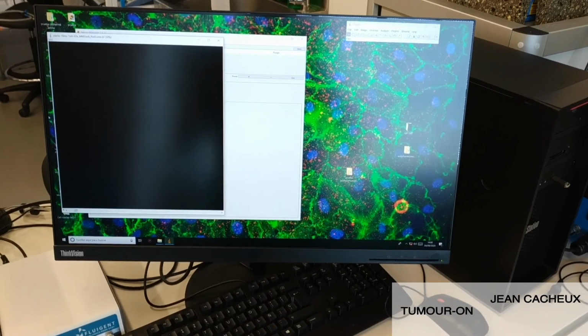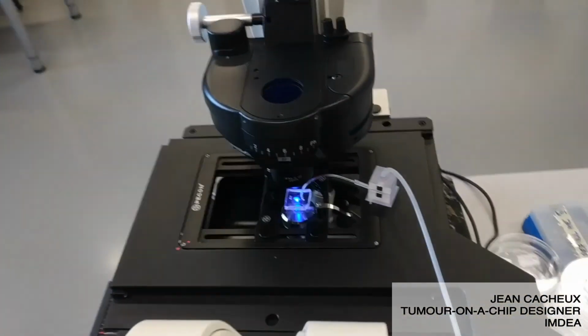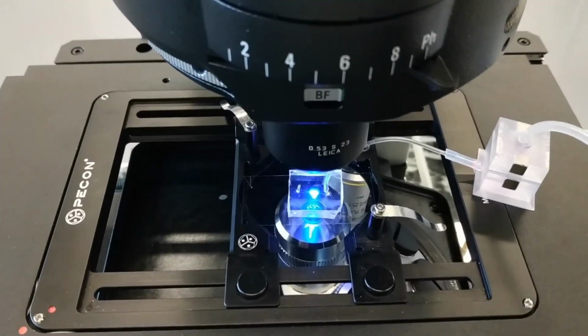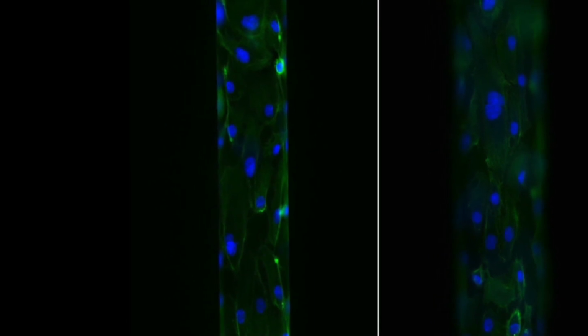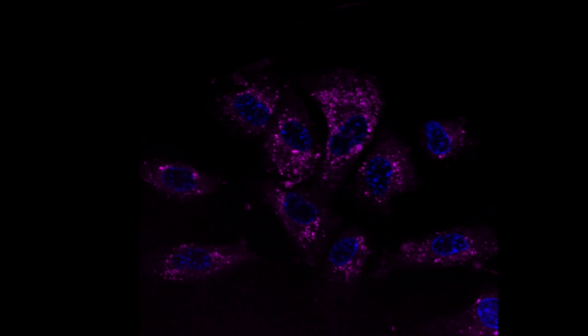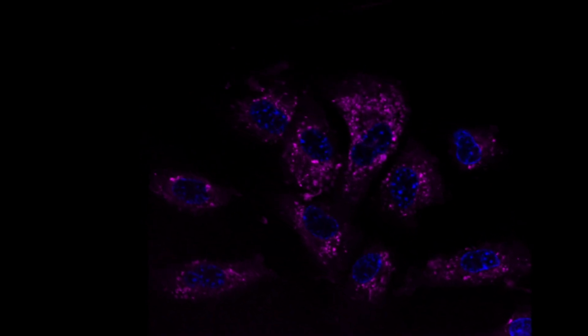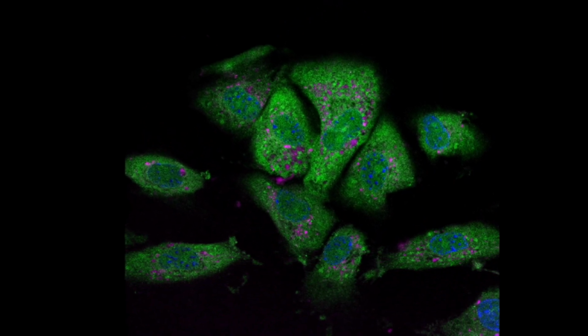We are developing artificial tumor microvessel on a chip devices. These devices comprise a microchannel with a diameter in the range of the tumor capillaries and semicircular geometry. Also, they serve as scaffold of human endothelial cells to form an artificial vessel-like endothelium. The devices are used to investigate the transport characteristics of nanoparticle-based anti-cancer drugs in the bloodstream, mimicking as close as possible the human physiological conditions. The microvessel devices are also employed to study how nanoparticles of different sizes or chemistry interact with the vascular endothelium, and how these get extravasated out of the vascular flow to the surrounding tissue into the solid tumors.